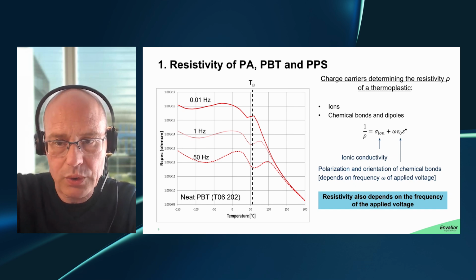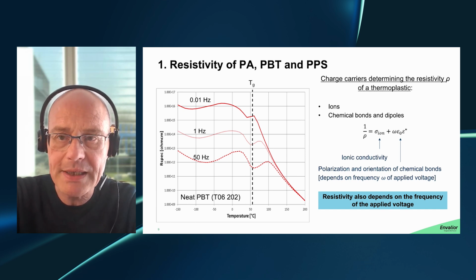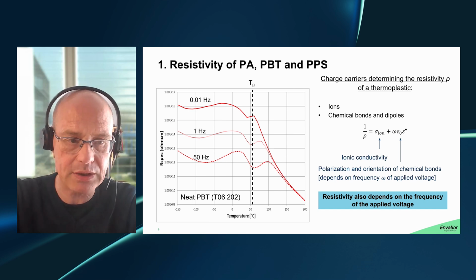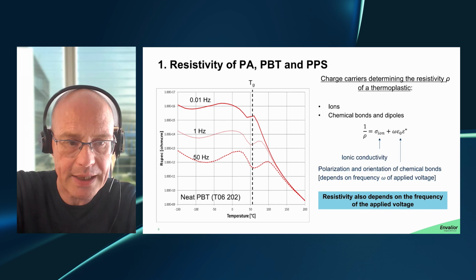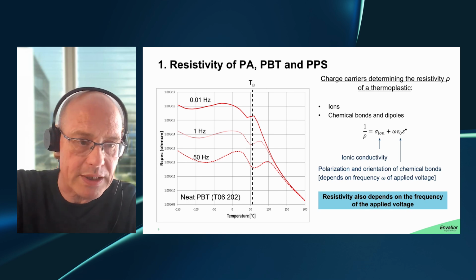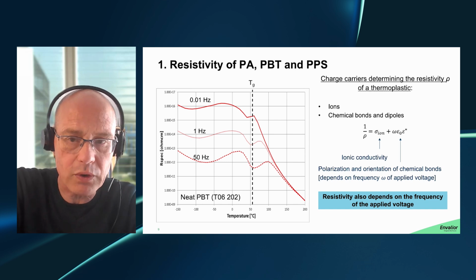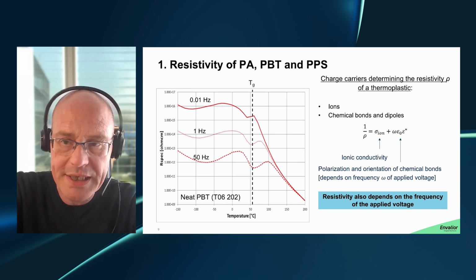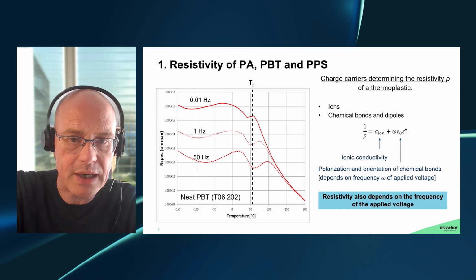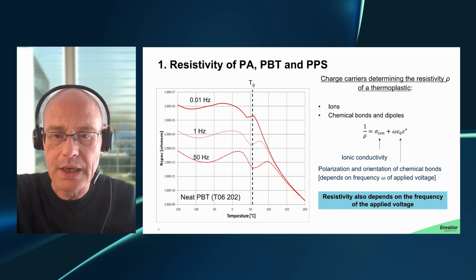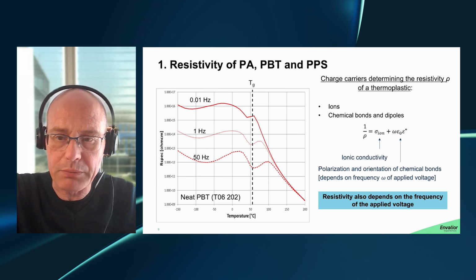Or if you want to have that displayed graphically, you look at the picture on the right. This is for a PBT, and there you see that at very low frequencies, close to DC, resistivity tends to be high because the bonds get polarized not very often, so there's not much current flowing. And if you raise the frequency to AC, then 50 Hertz AC, then you see that the resistivity comes down because there's now more current flowing through your material because you polarize the bonds more often. So in conclusion, the resistivity of a polymer depends on temperature, relative humidity, and on the frequency of the applied voltage.